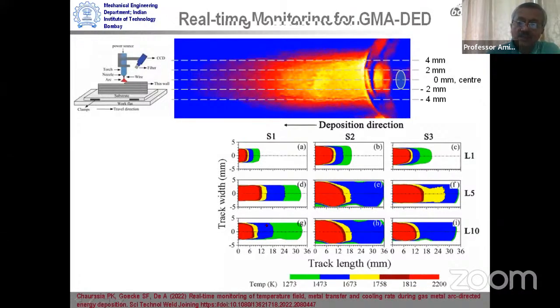Okay, and we can see for three different conditions, like a lower heat input, a high heat input, and a relatively moderate heat input with a high speed, how the melt pool on the surface is evolving. Not only that,